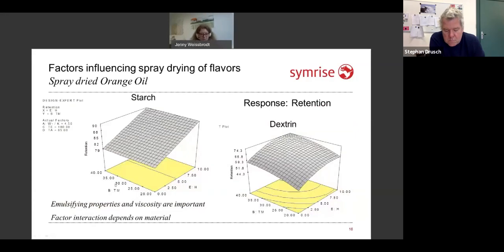We have, again, the solid content from 20 to 40%, and the homogenization time. We just used time here to have a continuous factor. It means 0 homogenization, 5 minutes, which is 1 pass at 200 bar, and 10 minutes means 2 passes at 200 bar homogenization pressure. You see, the finer your emulsion, the better is your retention for our orange oil within the nice emulsifying material.